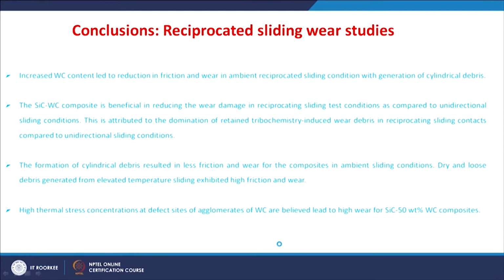Concluding these results from the reciprocatory sliding wear studies, increased tungsten carbide content resulted in a reduction in the friction and wear in ambient reciprocatory sliding conditions with the generation of cylindrical debris.